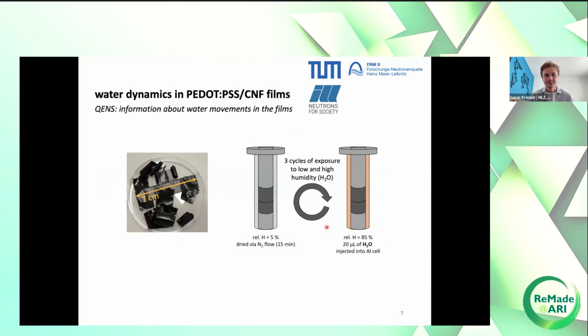And this is exactly what we did at the IN5 instrument at ILL, where we were interested then in the water dynamics. How does water move in our PEDOT PSS CNF films? And in this case, we took these freestanding films. For this experiment, that really came in quite handy, because we took these standard aluminum cylinder cells from IN5. That's basically an inner cylinder in an outer cylinder. And in the inner cylinder, we rolled around these PEDOT PSS CNF films and then put it all in the outer cylinder, closed it, and we were ready to measure. And by rolling this around the inner cylinder, we increased the scattering volume. And it's a very elegant way to still be able to measure relatively thin films.